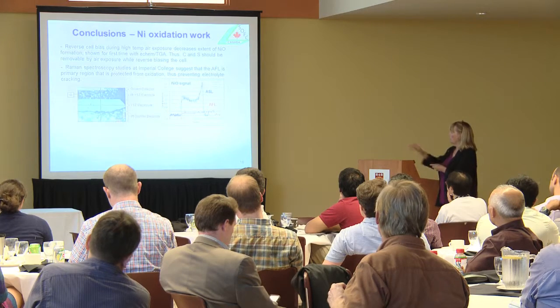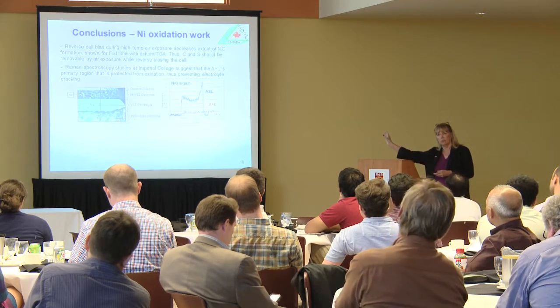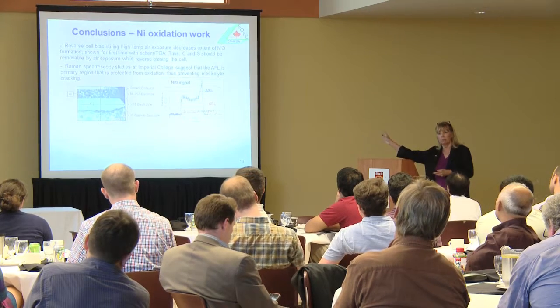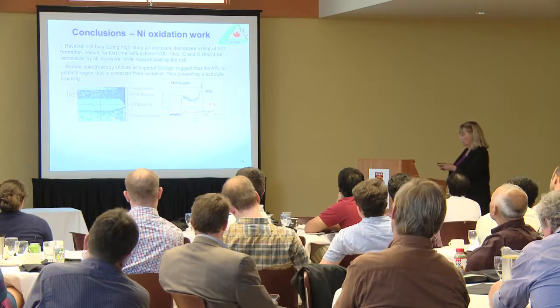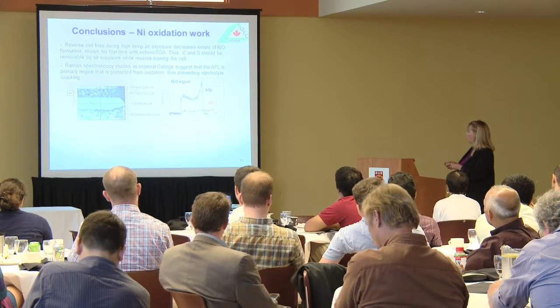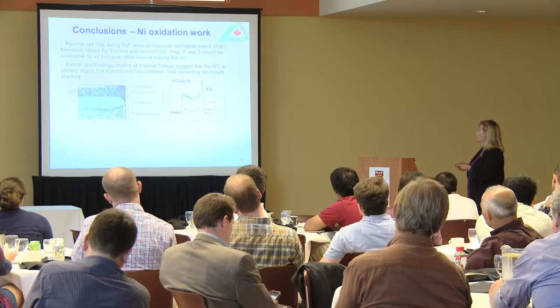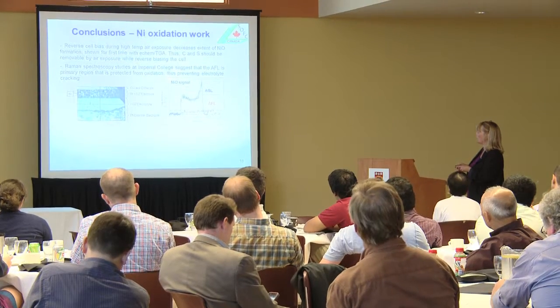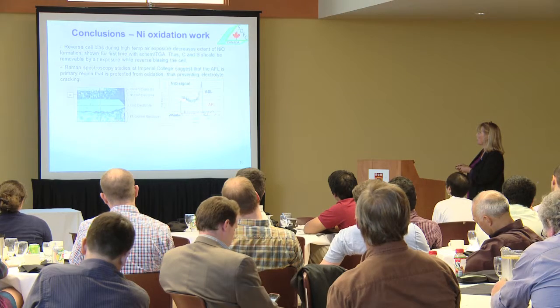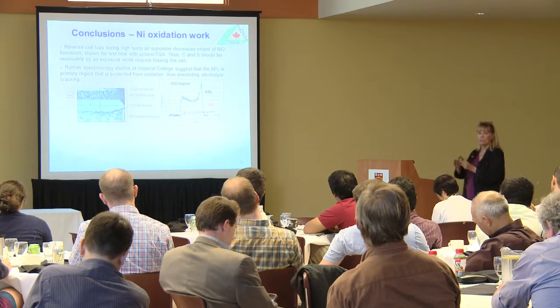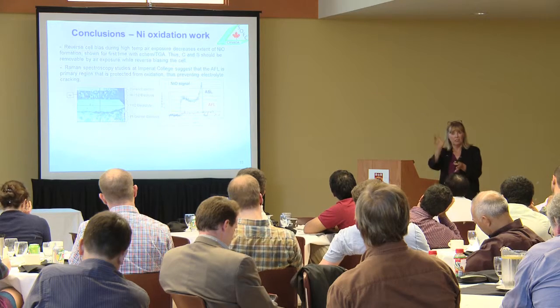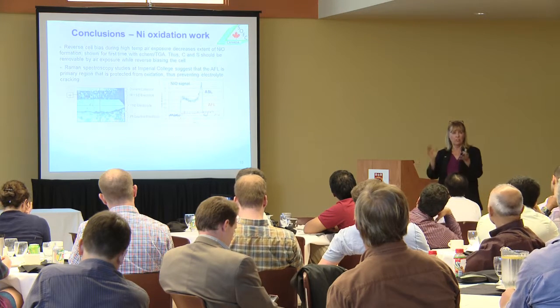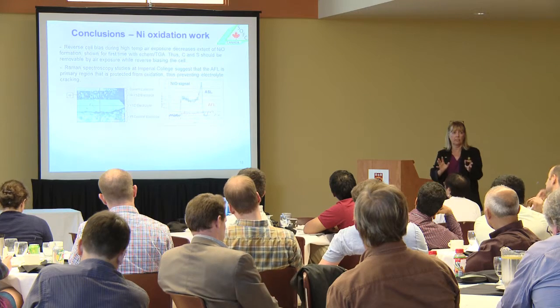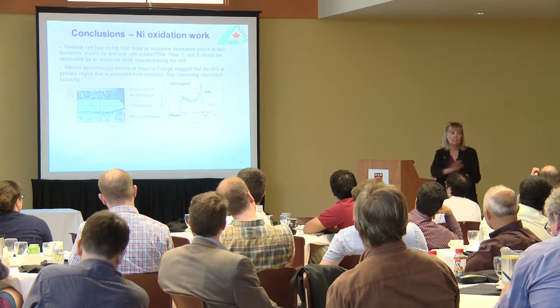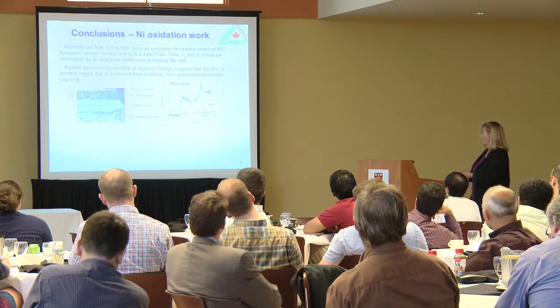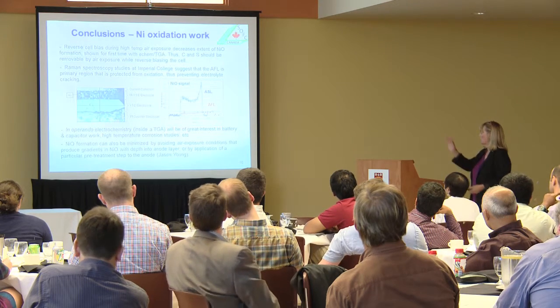You may not be able to see this very well, but this is the in situ Raman work that we've been doing with Rob Maher at Imperial. And what it shows is that if you track the amount of nickel oxide after one of these negative bias experiments, in the support layer, that's where most of the oxygen is, where all the electrochemistry is happening and where the electrolyte is almost not there. In other words, the negative bias has probably protected the right area of the cell. It's deep inside the anode. Okay, a couple little things. Maybe I can just do those two things together.